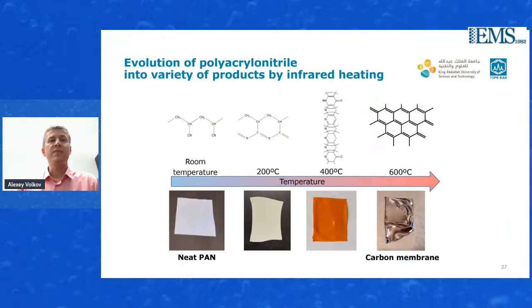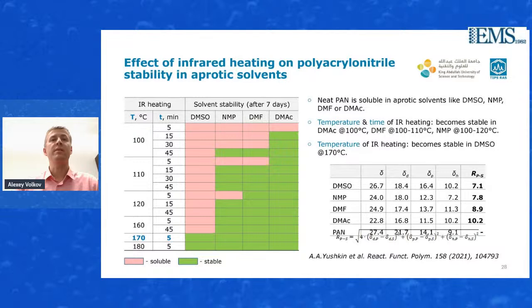And by using infrared, it's possible to go from the neat PAN to the carbon membrane. And for the carbon membrane, actually we need a lower temperature, something like 600C to get that, instead of what people are using, like 800-900C. And that's a good benefit of the infrared treatment, due to the lower temperature required to get the same material.